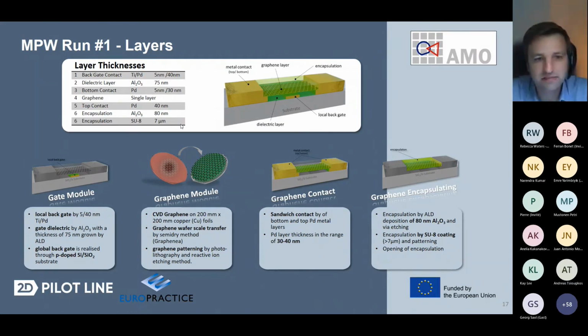After that, the graphene layer, which we provide here, is a single layer. This is grown on a 200 by 200 millimeter copper foil by our partner Graphenea, who will also do the graphene transfer in this case with the semi-dry method. And after the transfer is done on our substrate, the graphene patterning and all the following steps will again be done in our lab.